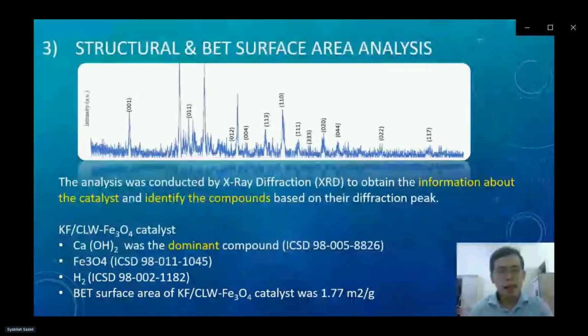Next is the structural and BET surface area analysis. The structural analysis was conducted by using X-ray diffraction to obtain information about the catalyst and identify the compounds based on their diffraction peaks. For the KF/CLW/Fe3O4, from the picture, it can be seen that Ca(OH)2 was the dominant compound based on the database ICSD 98-005-8826. Next is the Fe3O4 based on the database ICSD 98-011-1045. Then the last one is H2, ICSD 98-002-1182. The BET surface area of the KF/CLW/Fe3O4 catalyst was 1.77 square meters per gram.